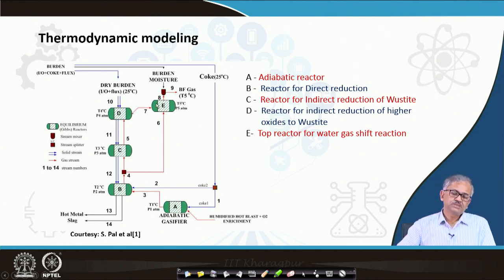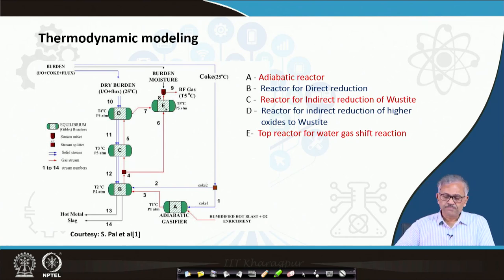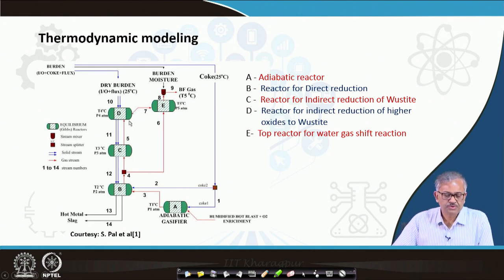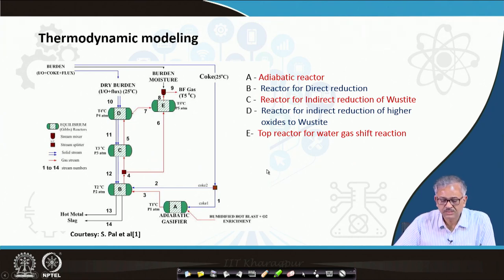The exit gas temperature is also determined by this thermodynamic reactor — based on this calculation you know what will be the exit gas temperature and composition. These reactors are calculated using the FactSage thermodynamic simulator software — for all reactors, gas composition and temperature can be calculated. Finally, you can also get the hot metal composition and slag composition, also calculated by FactSage.